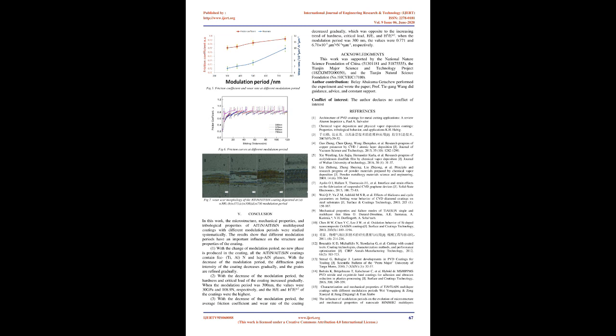To increase the resistance to plastic deformation, it is desirable to obtain materials that possess high hardness but lower elastic modulus values. With higher hardness and lower elastic modulus, the plastic deformation is lower, because the external load is distributed over a larger area and the stress distribution is more uniform. This behavior is then expressed by H/E and H³/E*². A high H³/E*² ratio, where E* equals E/(1−ν²), E is Young's modulus and ν is the Poisson's ratio, is valuable since it shows the resistance of the coating to crack.